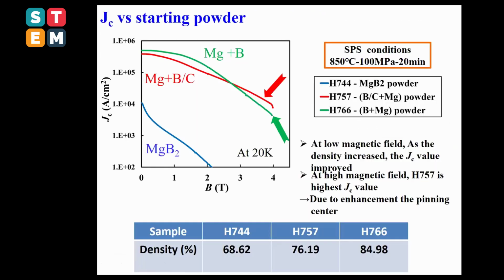Well, what do you name? I name here this JC, the critical current density, versus starting powder. This powder was prepared by a colleague from Japan, from SIT: magnesium diboride made by using nano-borons, or magnesium diboride where the boron was coated with carbon. What can we learn from this curve? First, all three samples were prepared in the same condition, 850 degrees C, 100 megapascal during 20 minutes.